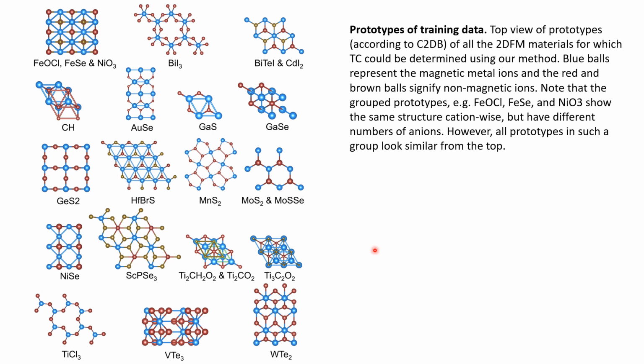A lot of these materials, around 50% actually, turned out to be antiferromagnetic upon close inspection by our code. The calculation for a lot of materials could not be finished because of several computational challenges, which we have detailed in the paper. In the end, we could successfully determine the Curie temperature of 157 materials. 157 materials were verified to be ferromagnetic, and we could successfully determine their Curie temperature from C2DB. And we use these 157 data points as a training set for a machine learning model.